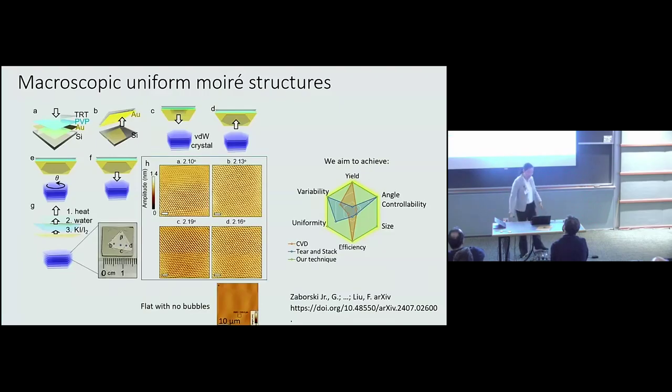With that, we can create a twisted van der Waals interface with lateral dimensions of millimeter to centimeter scale. And we can randomly sample 4 different locations, and this is piezo response force microscopy, or torsional force microscopy, whichever name you call it. What you see here are not atoms, but the moiré structures in real space. And from the periodic pattern of the moiré structures in real space, we can back calculate the twist angle. And you can see that the twist angle is very consistent across the centimeter scale surface.